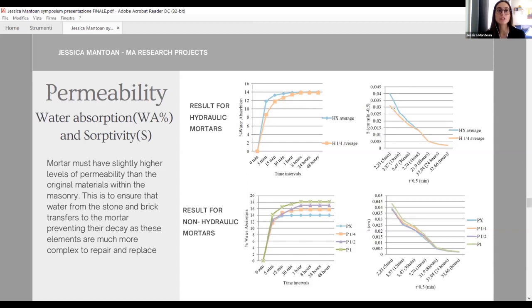That is a really positive result in relation to hydraulic mortar, because usually one of the negative characteristics of this type of mortar is that they are mechanically weak, because often the nucleation of salt in the capillaries creates a lot of disruption in the material. In this way, if the material is less able to absorb water through the capillaries, that kind of decay mechanism can be mitigated. Completely different results are shown for the non-hydraulic mortar, where with the increase of barium hydroxide additive, the ability of the mortar to absorb water also increases. And quite surprisingly, the sorptivity is not changed for any of the samples containing barium hydroxide.